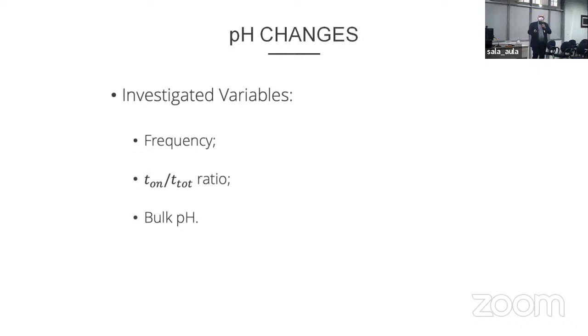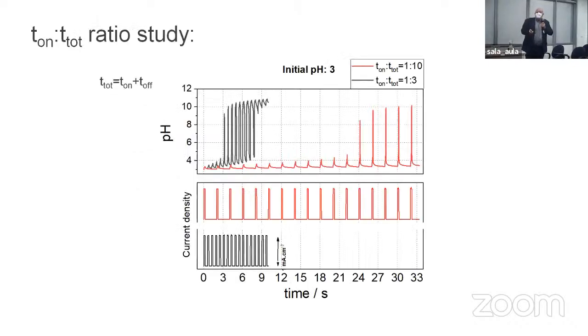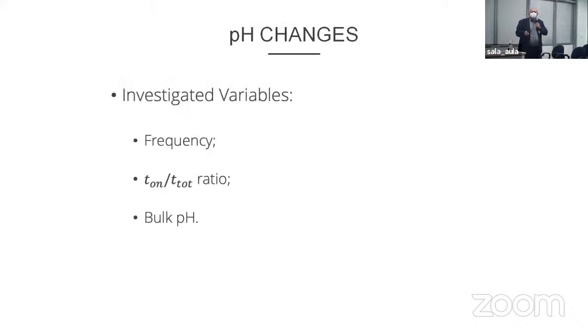Then we start to investigate what we can do. And we propose at the beginning to use a step with an off time, not a continuous current value, but like this: start, stop, start, stop. Then we give the system time to transport the excess of hydroxyl ions from the interface into the bulk solution. And for sure, we use different conditions. We study the frequency, we study the difference of T on, that is the time where the current is on over the total time of one square wave, and the initial bulk pH.